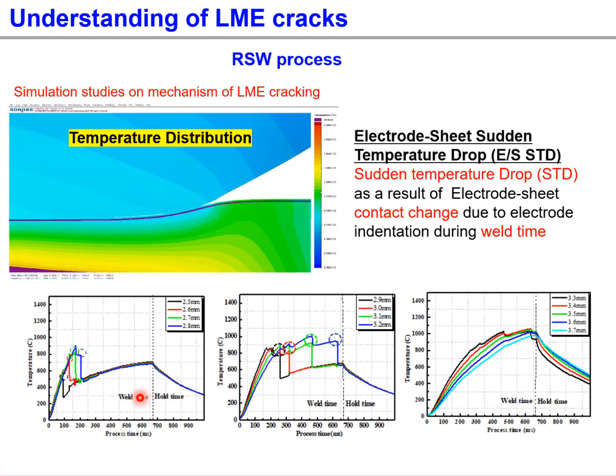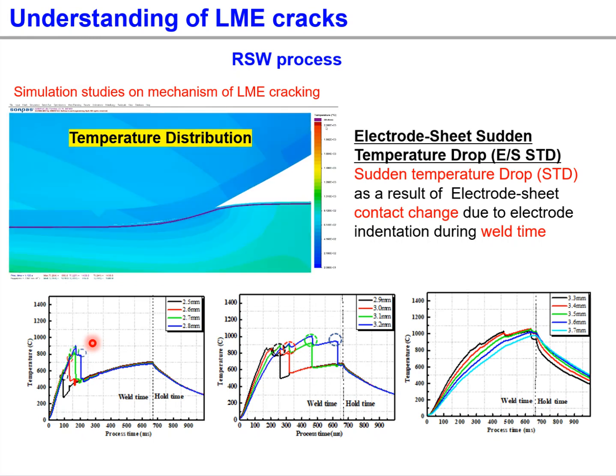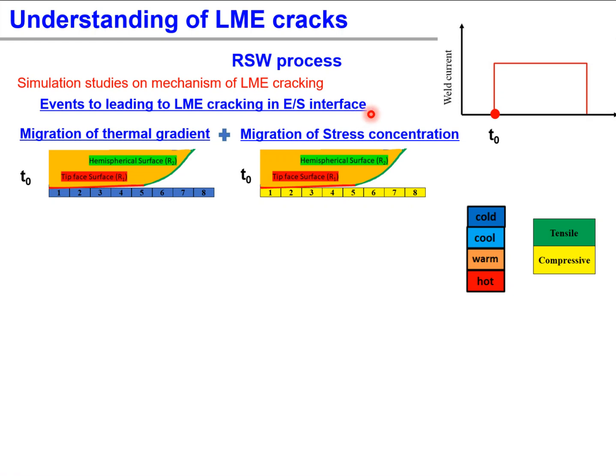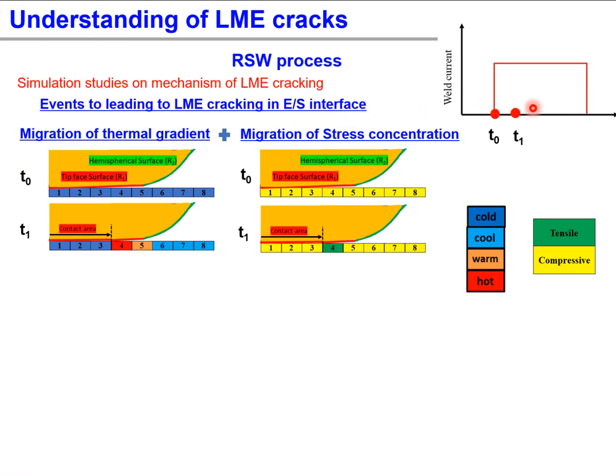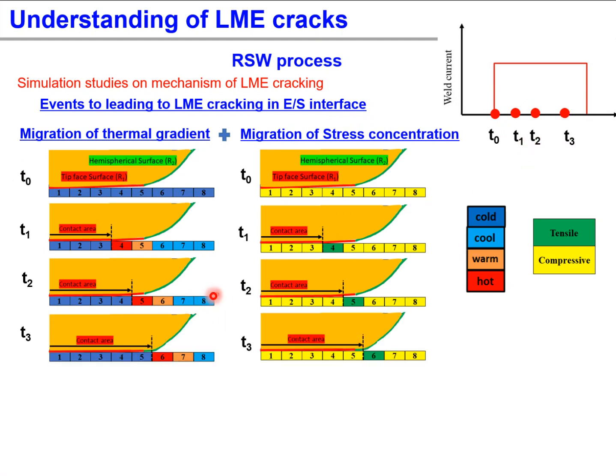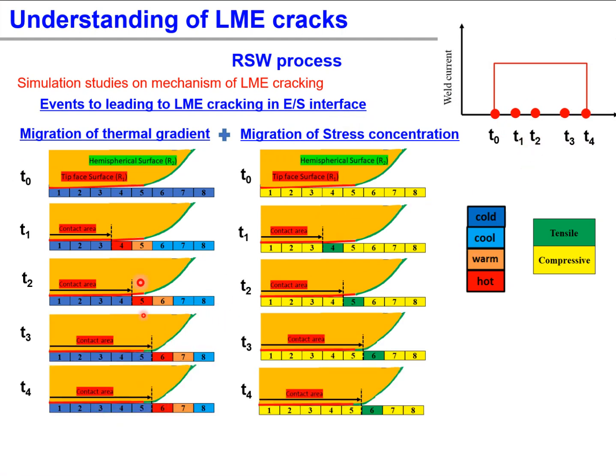Several physical electrode-sheet contacts have been observed at different locations, with a sudden temperature drop at different locations and different times during the welding time. By performing the simulation with welding times of T0, T1, T2, T3, and T4, the new contact between electrode and sheet surface established a sudden temperature drop which satisfied the thermal gradient for the tensile stresses. So each time during the welding, it established the thermal gradient and tensile stresses.